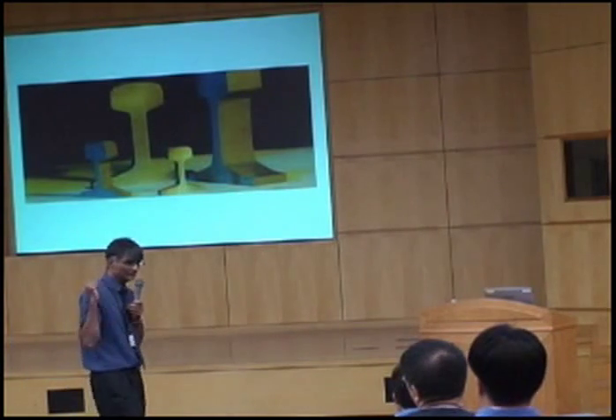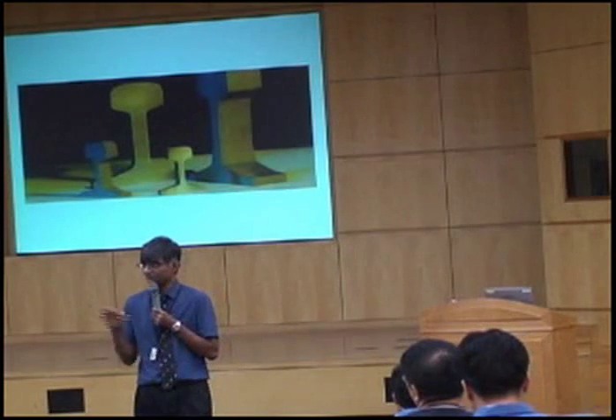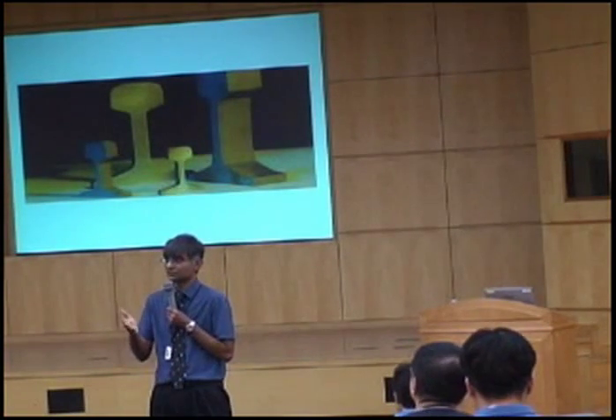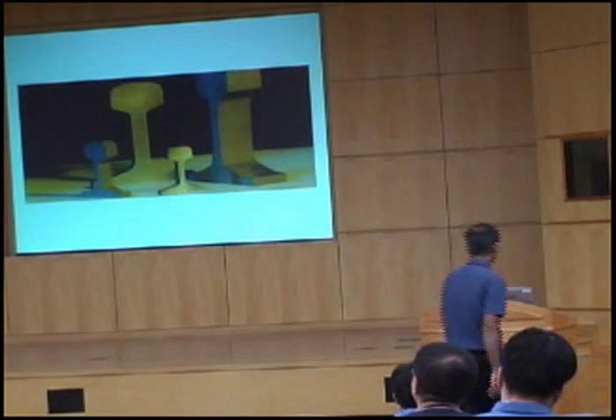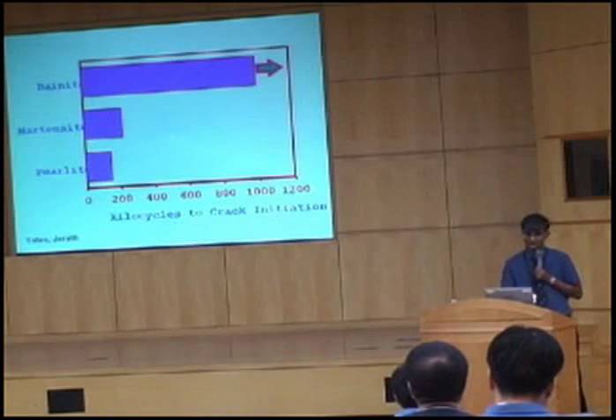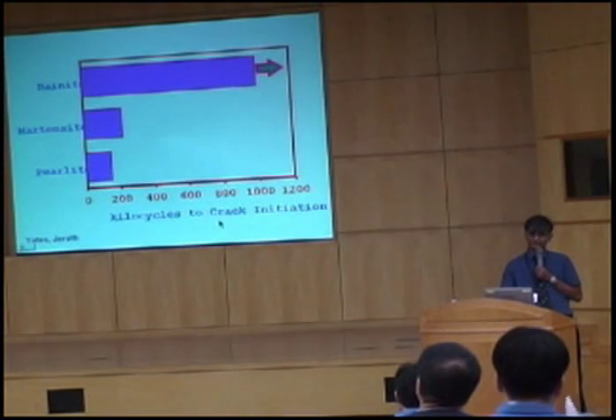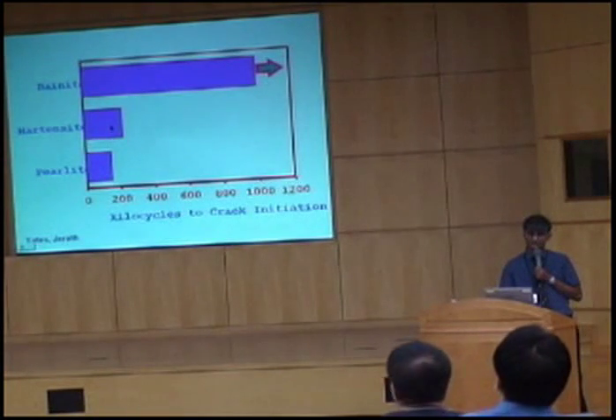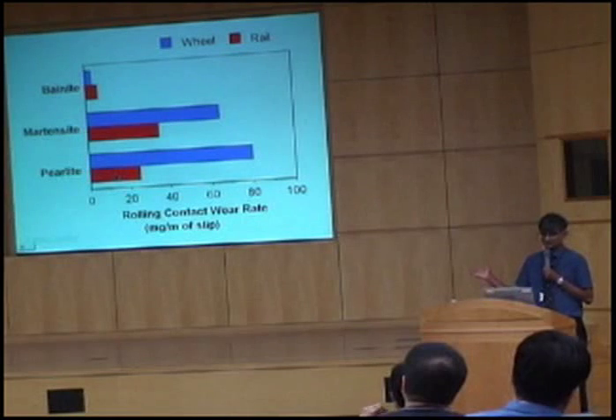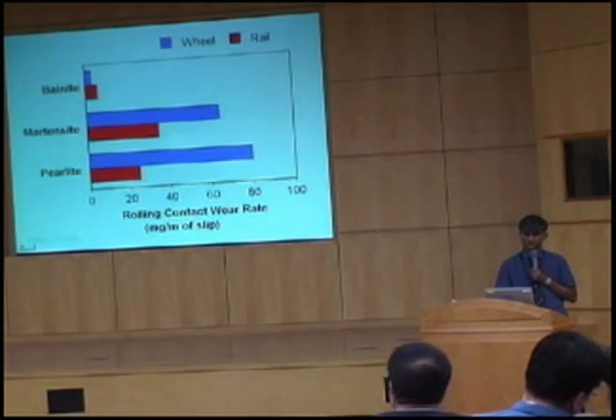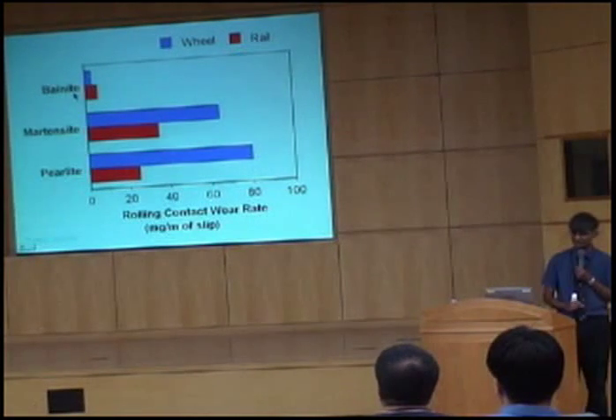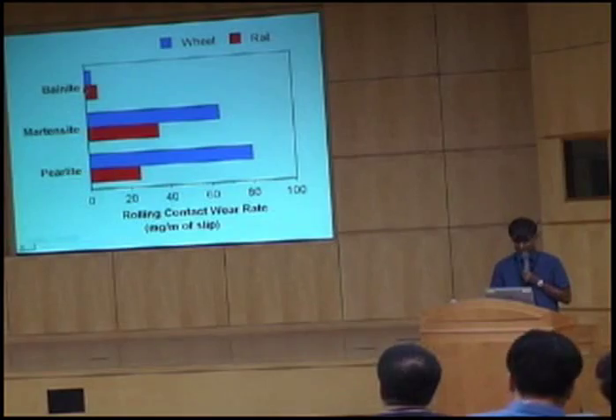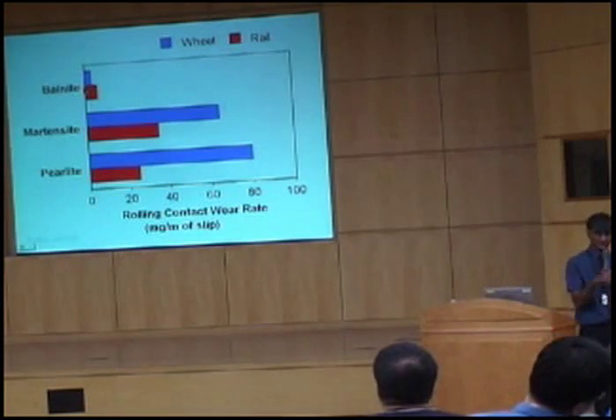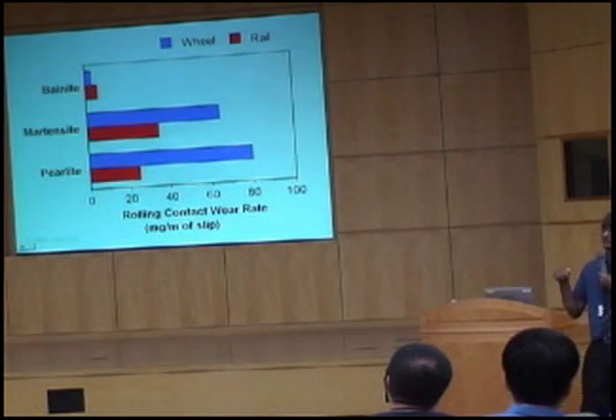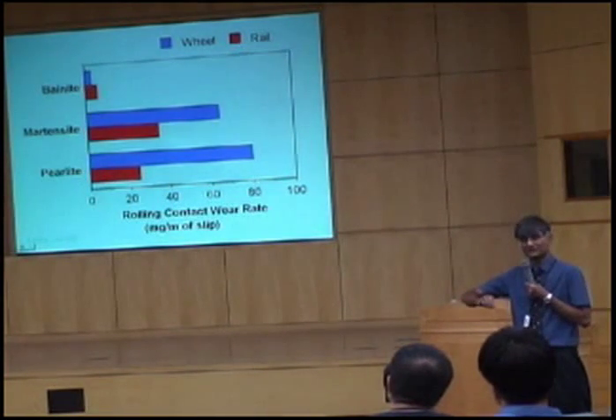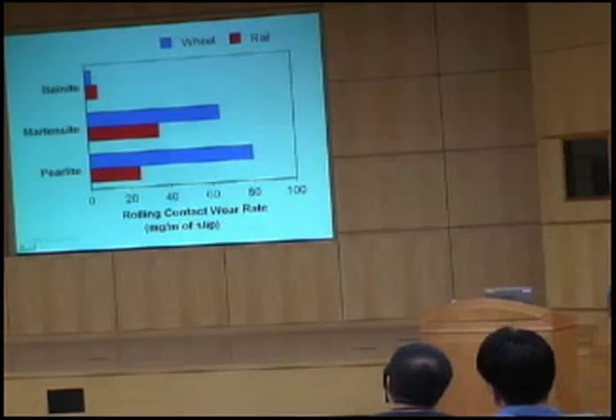Okay? Here we have produced rail steel which is completely free of carbides, based on the bainitic microstructure of bainitic ferrite plates and carbon-enriched retained austenite. And if you look at the rolling contact fatigue resistance, it is very, very high compared with a martensitic or pearlitic rail steel. And here you have the wear rate, both on the wheel and on the rail. And you can see this new carbide-free bainitic structure has much better wear resistance on both the rail and the wheel, because it doesn't produce debris. There are no brittle carbides, so it deforms rather than producing lots of fragments, abrasive fragments.